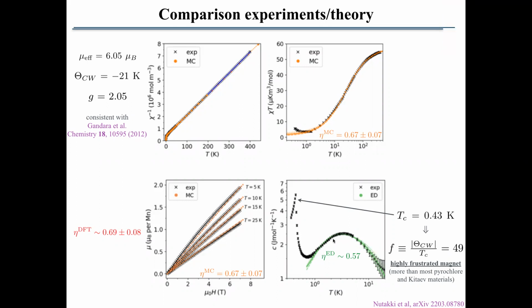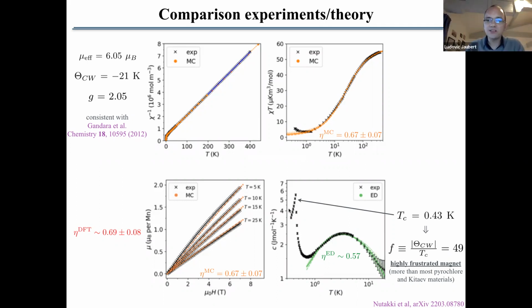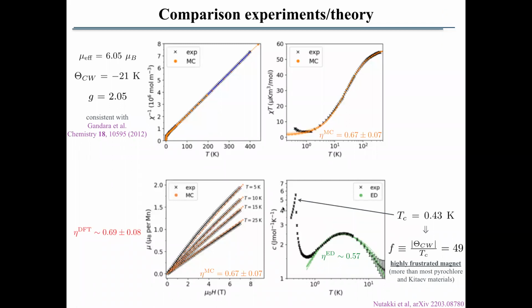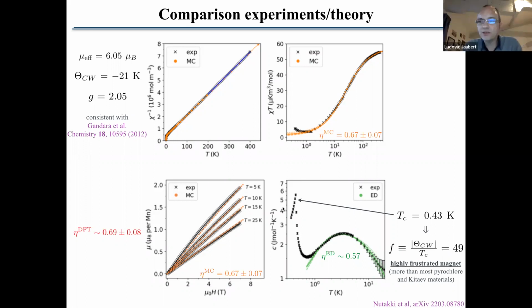What is TC here? I'm sorry, what is TC? I mean, I'm still confused. TC is the transition temperature. So the system at low temperature at 430 millikelvin orders into a long-range ordered state. Okay. So what kind of magnetic structure orders to? We don't know, because the problem is that it's an organic material, so there are hydrogen ions, and hydrogens absorb neutrons, which means you cannot use the usual neutron scattering to probe the magnetic structure. So it needs more work to be able to pinpoint the nature of this magnetic order.